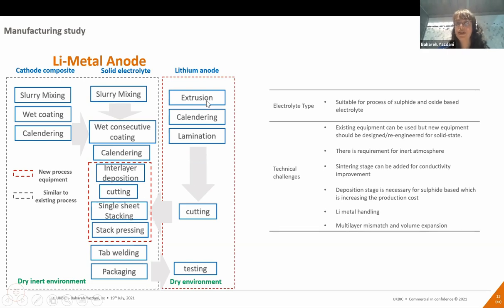The lithium anode section requires extrusion, calendering, and lamination, followed by stacking to the cathode and solid electrolyte layer. But basically, in this technology, the cathode composite will be deposited on the current collector and followed by the solid electrolyte on top of that. So it's a consecutive coating of the electrolyte on top of the cathode composite. So it's a double layer on top of each other. This technology, we haven't had experience with on a massive scale before, but it should be possible and doable, and then followed by lithium integration as a third layer on top.